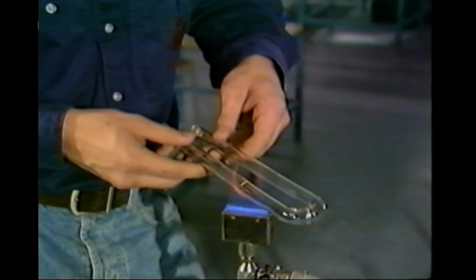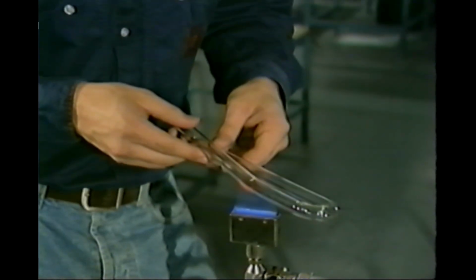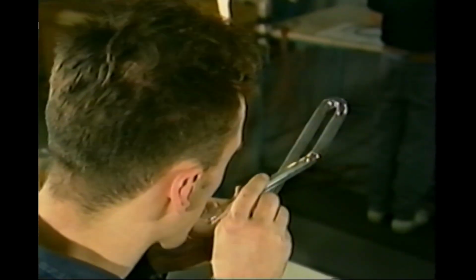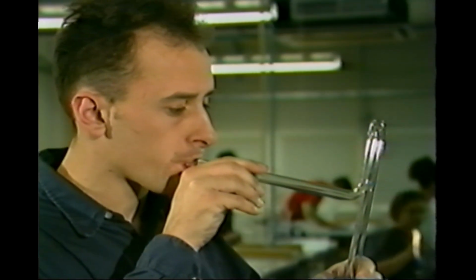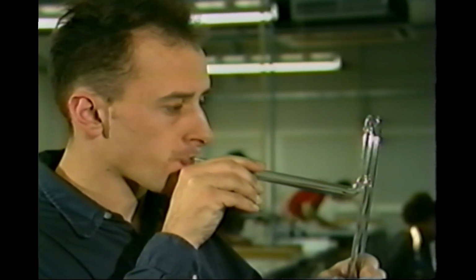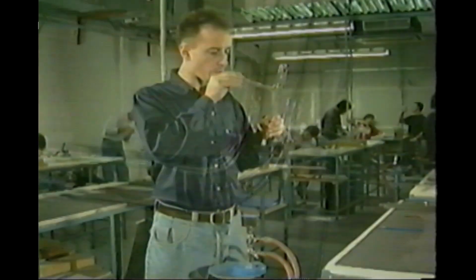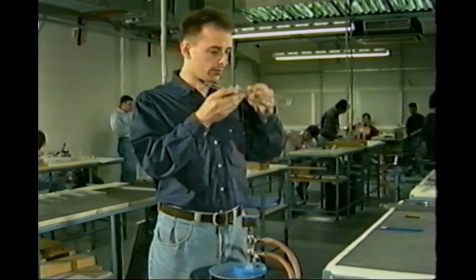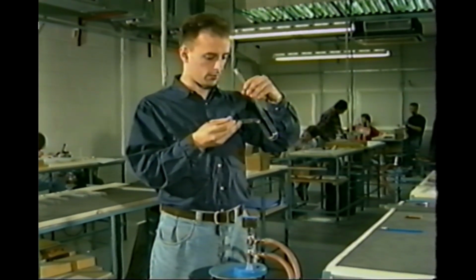This will become the outside radius of the right angle bend, and at the same time raise the sidearm in the right hand and create a small radius in the heated area with the mark centrally situated, whilst keeping the left sidearm horizontal. When the outside radius extra melt is complete, raise the tube up to eye level directly in front of the face. Slowly move both hands, shaping away from each other to produce the bend, and blow until tube diameter is restored to the bend. The correctly performed bend will have the pencil mark in the center of the inside radius, correct diameter, and from an end-on view, the right side arm and return bend should be at right angles to each other.